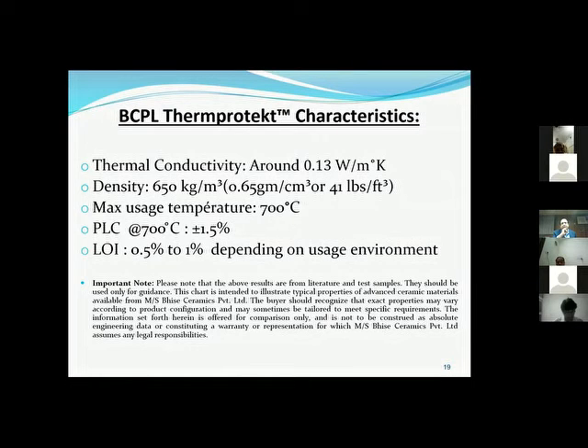The thermal conductivity is around 0.13 to 0.15 watt per meter Kelvin. The density is 0.65. The density of water is 1. So this is an insulation that will actually float on water. The max usage temperature is about 700 degrees centigrade.